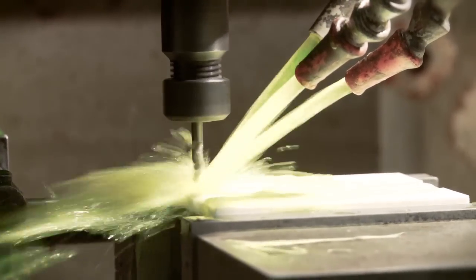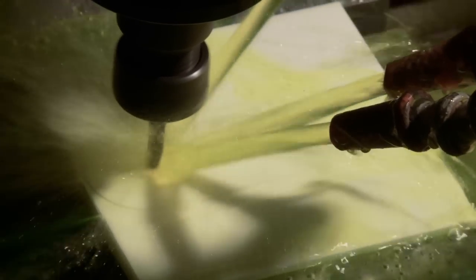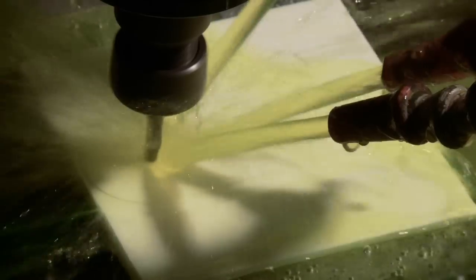For a quarter inch drill, a spindle speed of 300 revolutions per minute is suggested at a feed rate of 5 thousandths of an inch per revolution.